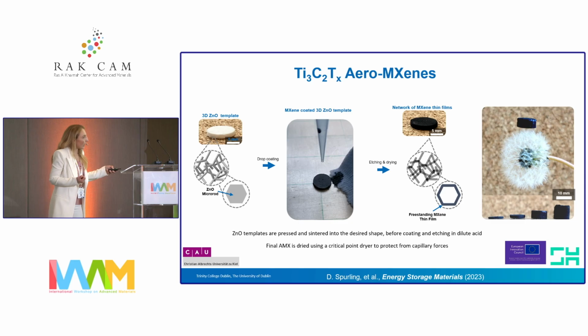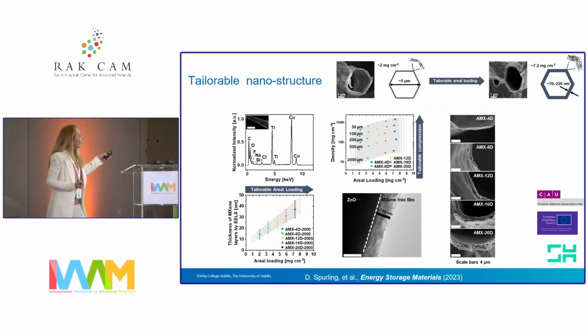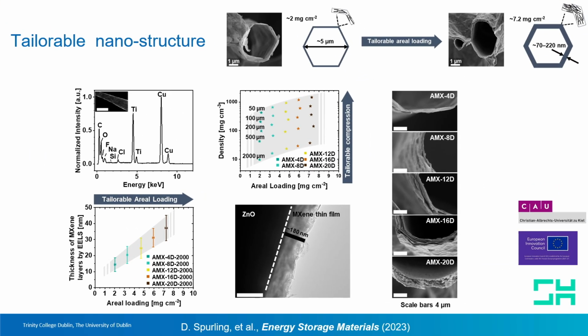They've been in the process of being commercialized, actually, as an outcome of this very nice EIC transition grant, because we have two ways of controlling these devices. One is that we can tailor the nanostructure of these tubes. How? Simply by dipping more MXene dispersion onto the template. So you can make these walls thinner or thicker,